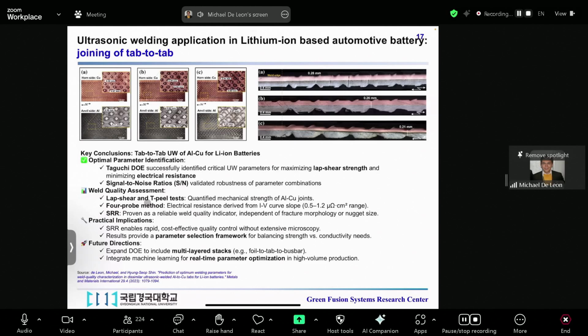Microstructural analysis via SEM-EDS revealed critical insights, such as aluminum atoms diffusing more actively than copper during ultrasonic welding, likely due to higher atomic mobility. Fortunately, the low melting or welding temperature inherent to UW limits the interdiffusion, which restricts harmful intermetallic compound formation, which is very beneficial to the joint.